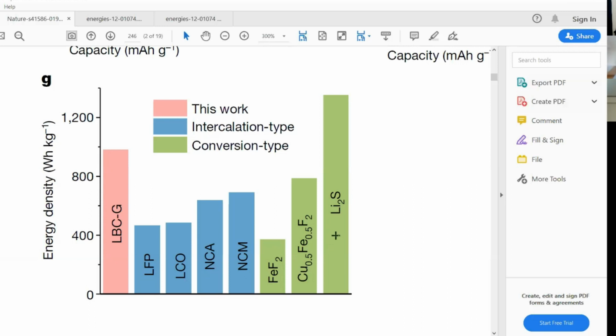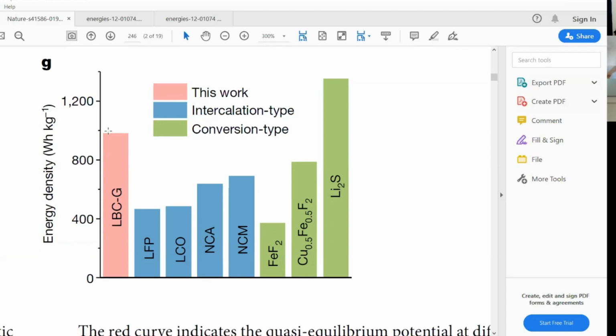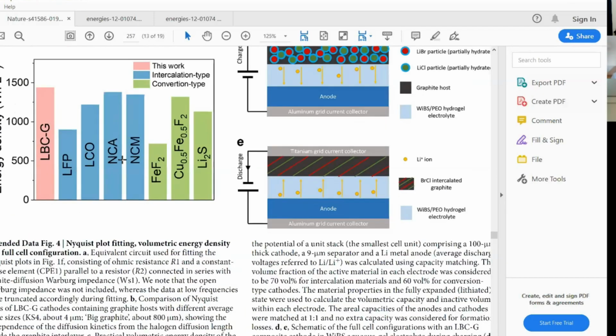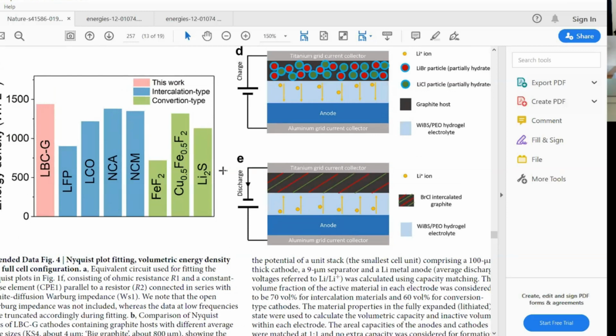So the future is here, at least for some academic groups, saying that we're probably going to use the conversion type like lithium sulfur or even lithium air. But compared to lithium sulfur, based on the weight, the energy density is a little bit lower. But this is a volumetric energy density. Actually, lithium sulfur normally uses a lot of low density carbon host, right? So if we compare the volumetric energy density, this technology is even higher than lithium sulfur.